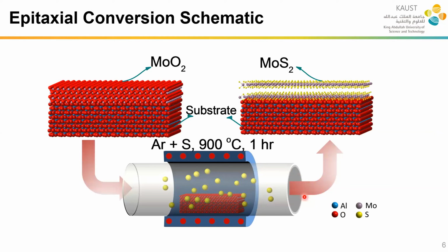So here is our process. We are thinking if we can prepare a high quality precursor by epitaxial growth. We found that moly oxide can be a very good precursor for moly sulfide, because it can be epitaxially grown on c-cut sapphire substrate. As we know, c-cut sapphire substrate is already used in the industry. So if we can grow the high quality moly oxide precursor on c-cut sapphire substrate, and then get high quality moly sulfide, the industrial compatibility will be easy to reach.